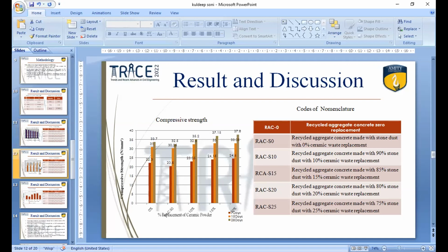Complete replacement with stone dust makes concrete a little stiff and weak due to a decrement of slump value by 3 mm and a drop in compressive strength by 2.42%, but these values come under the permissible value. Therefore, complete replacement of conventional sand is possible with stone dust.